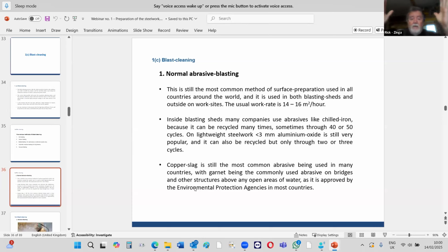All abrasives come in 25 kilogram bags. You just top up your pot and you measure, you'll see the profiles are going very deep again. It's as simple as that. And you keep on going. And because it's chilled iron, it breaks down. Eventually it becomes a dust and it gets sucked out your air vent and blown into the atmosphere, lands on the ground and becomes ferrous oxide. So it's completing the circle of life. So it's not detrimental to the environment. It's completely natural, completely normal.